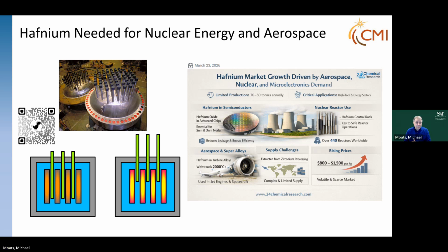Hafnium is also needed for nuclear energy, but also aerospace. So the hafnium that we separate isn't just thrown away, it's also very valuable. Hafnium, because it has that higher neutron cross-section, is used as control rod. You can see the control rod sticking up out of the reactor here. All the control rod does is they can lower or raise it to allow more neutrons to flow between the fuel rods, which provides more energy to heat up the water. You lower them and you slow down the reaction. So this is a way to control your reactor. Most of the hafnium in the world is actually used in aerospace applications, but again, we're focusing on nuclear energy in this talk. Hafnium and zirconium are really important for the application.